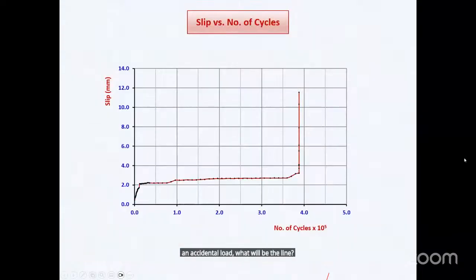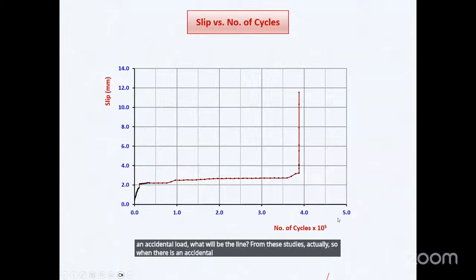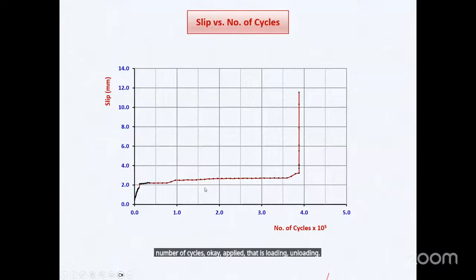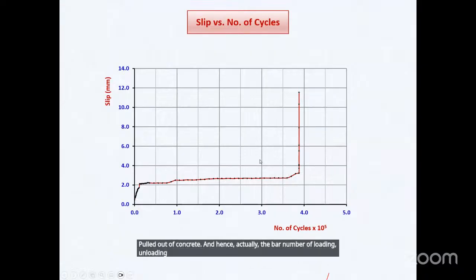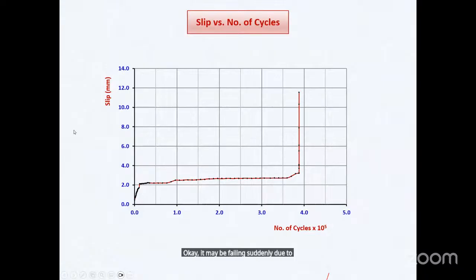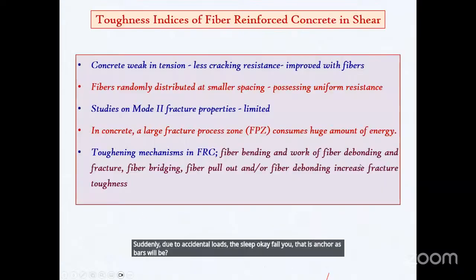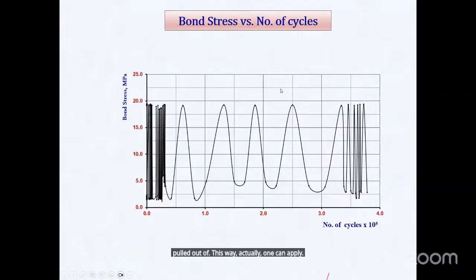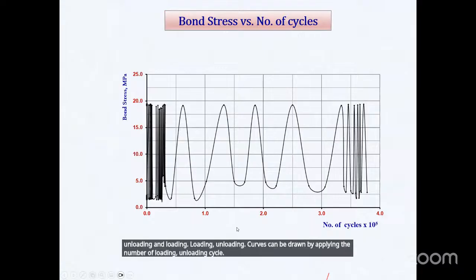From the studies, when there is an accidental load, the slip exceeds the number of cycles applied, that is loading and unloading, and the slip significantly increases. That means the rebars are pulled out of the concrete. Hence, it may fail suddenly due to accidental load. So this is slip versus number of cycles. Slip gradually increases with the number of cycles, but suddenly due to accidental loads, the slip failure occurs, that is the anchorage bars will be pulled out. This way, one can apply loading and unloading cycles, draw loading-unloading curves, and study the bond stress.